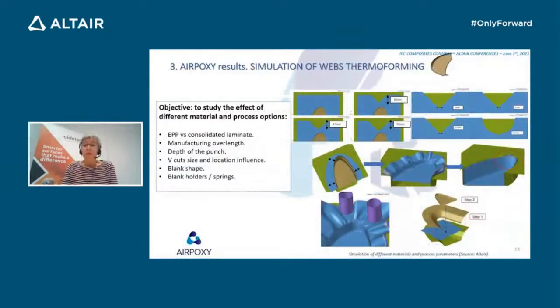Next, the models were adapted to simulate the 2 elements that will be produced by thermoforming: the longitudinal stiffener of the fan cowl demonstrator and the webs of the leading edge demonstrator. In the case of the webs, several material and process options were studied in order to define the parameters that best avoid wrinkles and delaminations. Based on the results obtained, the type, geometry, and holding system of the blank were defined. The best results were obtained with a punch in 2 steps, combined with a V-shaped cut, the depth without wrinkles being 10 millimeters. It was observed that springs were not a good option, as they add much complexity without improving the quality significantly.